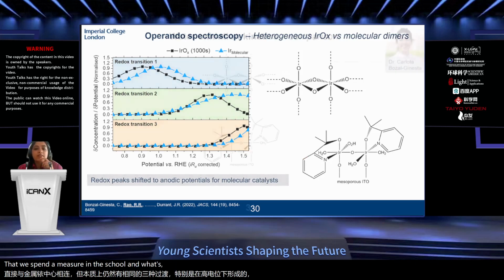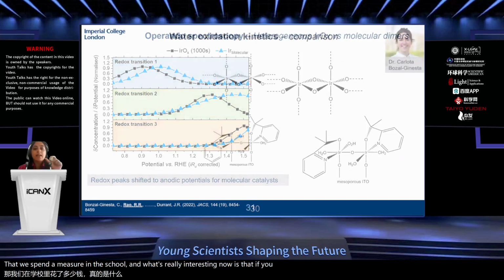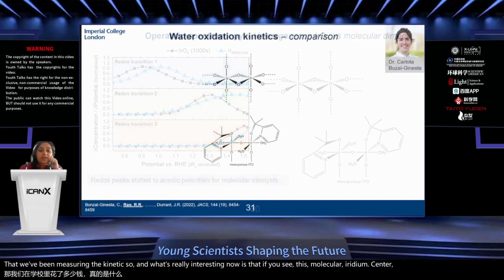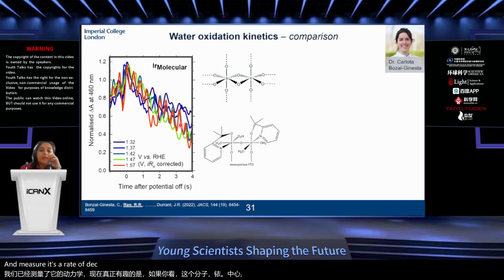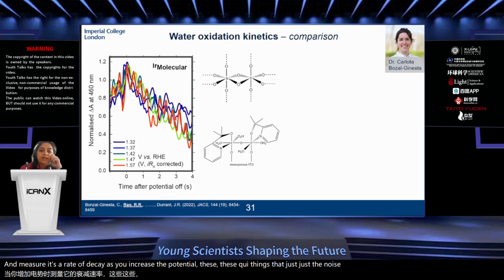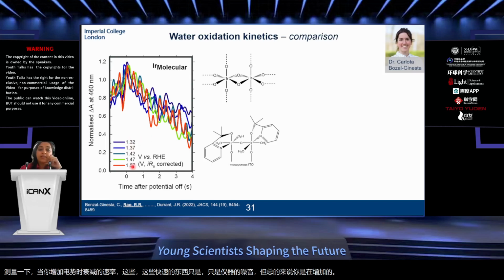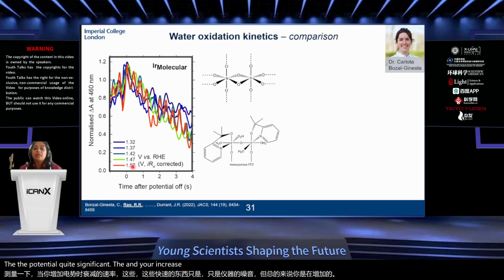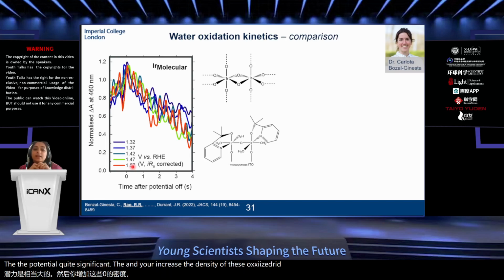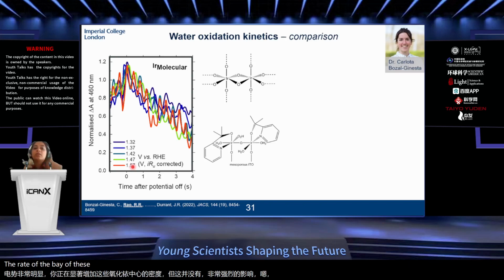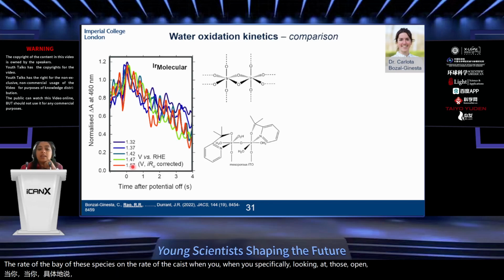And what's really interesting now is that if you take this molecular iridium center and measure its rate of decay as you increase the potential, these squiggly things are just the noise of the instrument. But by and large, you're increasing the potential quite significantly, and you're increasing the density of these oxidized iridium centers quite significantly. But that doesn't have a very strong effect on the rate of decay of these species, or on the rate of catalysis when you're specifically looking at those open circuit decay measurements.